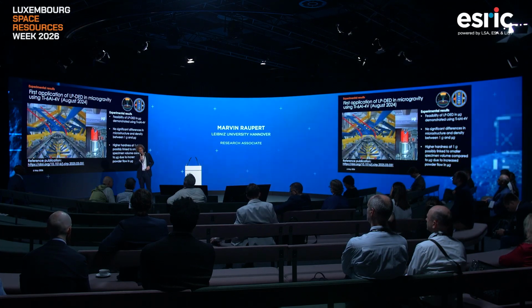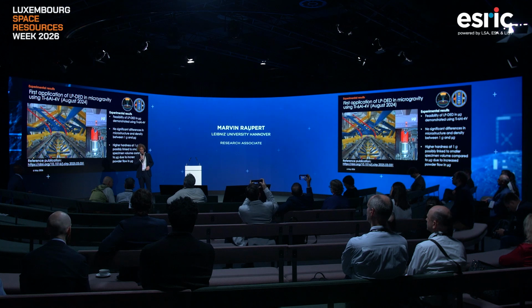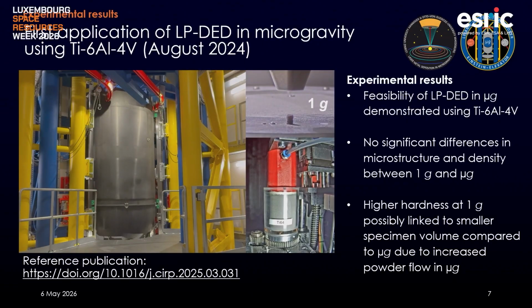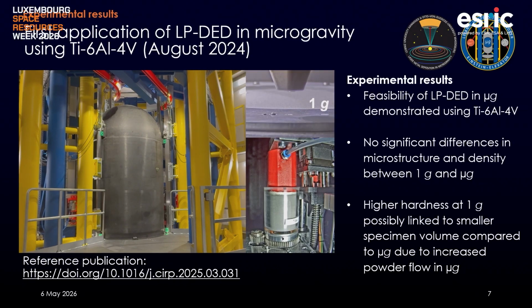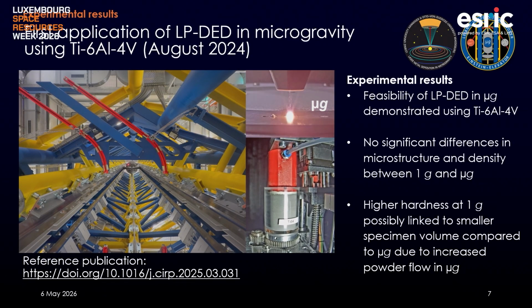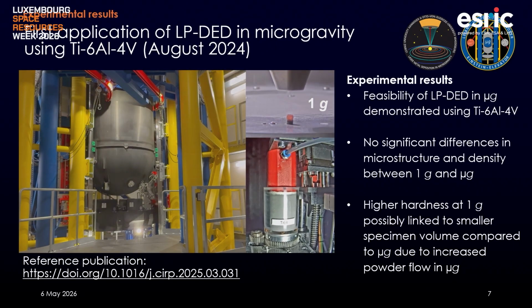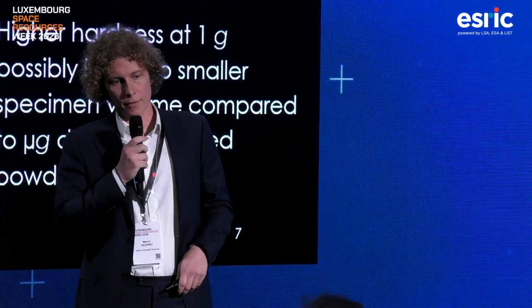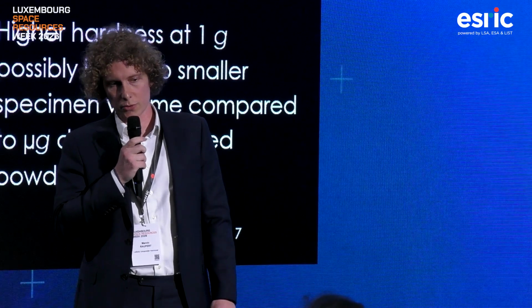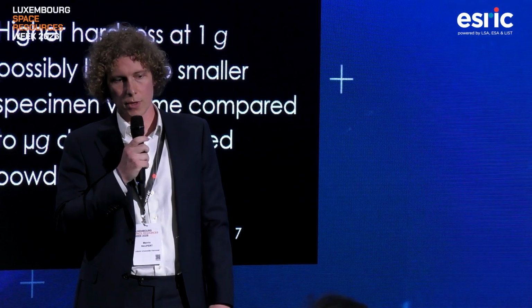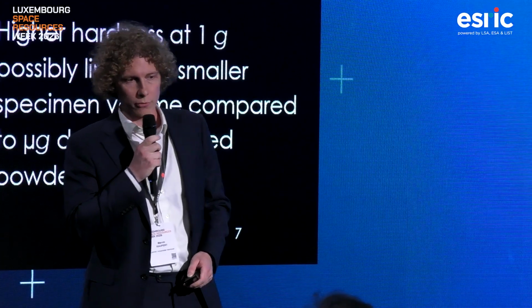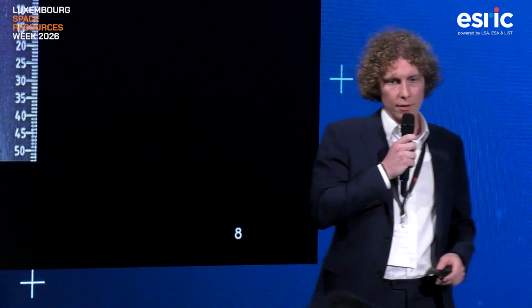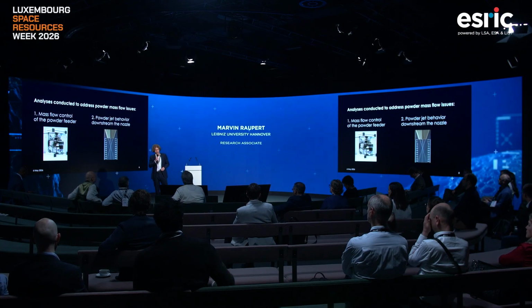And here, last year in this Congress, I presented you the first results of the specimens manufactured in microgravity from August 2024. We showed that it is possible to use this manufacturing process under microgravity. We have seen no significant differences in the microstructure and density between Earth gravity and microgravity, but there was a higher hardness at 1G, which was possibly linked to a smaller specimen volume compared to microgravity due to the increased powder flow in microgravity. So, and this is the topic. These are the 2 topics for my presentation today.